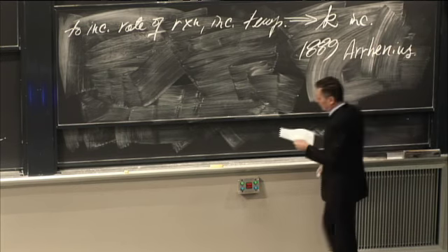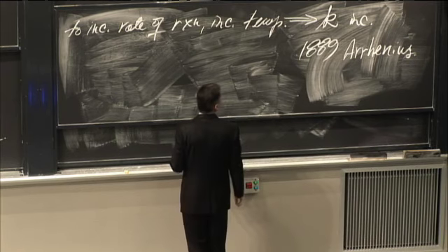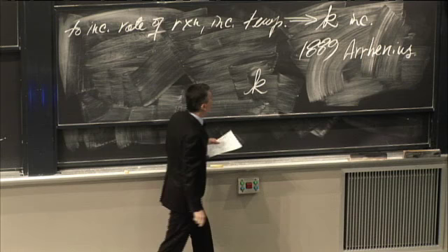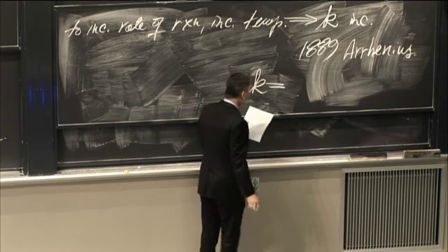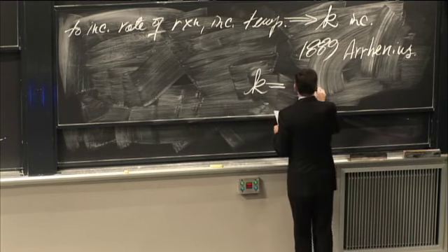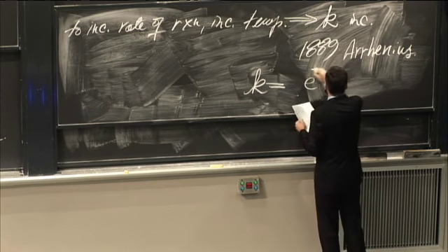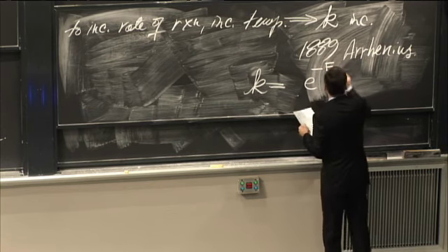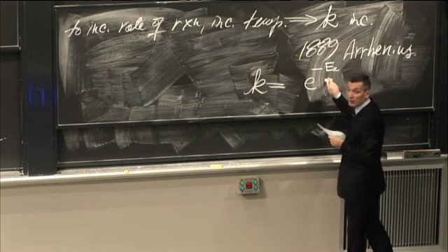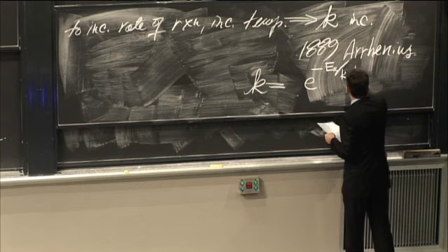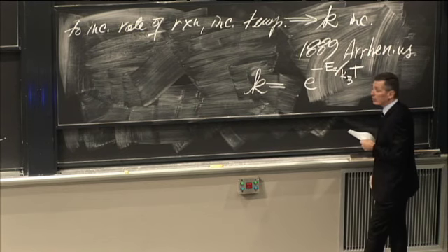Arrhenius. And what Arrhenius found, he found that the rate constant varied with temperature in the following manner. Rate constant goes as the exponential of the ratio of minus some quantity called the activation energy, E sub A, and I'm going to tell you what that means in a minute, divided by the product of the Boltzmann constant and temperature.